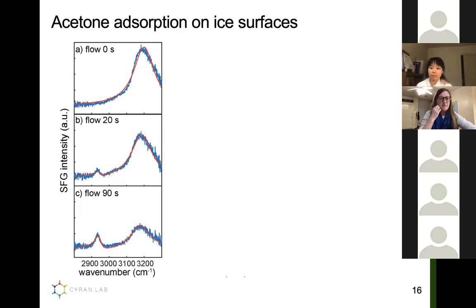So here at 0 seconds, we can see that we get a spectrum. The peak for the ice-air interface is showing up a little bit shifted from that of water, but you can see that we still have the hydrogen-bonded OH stretch vibrations here. Then I vapor deposited acetone onto the surface in different allotments of time. Here is an example spectrum of 20 seconds of flowing acetone on the surface, and then 90 seconds of acetone on the surface.